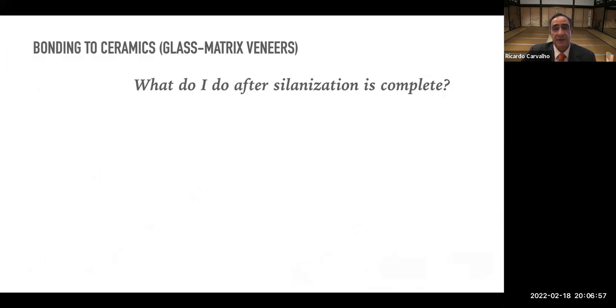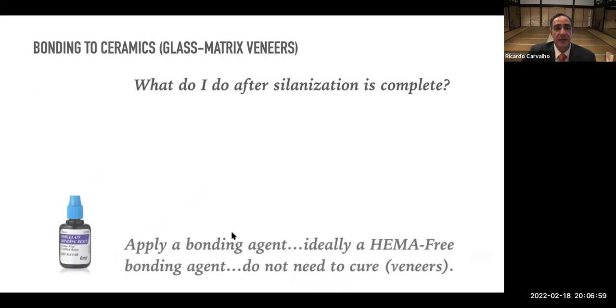And okay, what do I do now after the silanization is complete? Well, I should apply a bonding agent to my ceramic surface. And the reason I should apply that is simply because I have a surface that is full of small porosities. I have a surface in which I silanized the surface into those small porosities. Then I need a very fluid, low viscosity bonding agent in order to be able to penetrate into those porosities and accomplish the micromechanical and the chemical adhesion that I'm looking for.